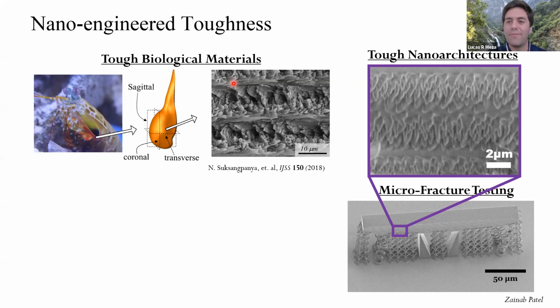So it depends on whether you have fiber pullout, breakage, friction, interlocking, or unwinding of polymer molecules. Something like spider silk is incredibly light and strong - it's actually a tensegrity, coincidentally, with beta pleated sheets that are stiff and allow it to stretch to 50-60% strain despite being super strong. So the nonlinear behavior of biomaterials is particularly interesting, and that's the complexity. That's why I'm interested in toughness - strength and stiffness on their own are interesting but a bit more predictable, whereas toughness is entirely uncharted territory.